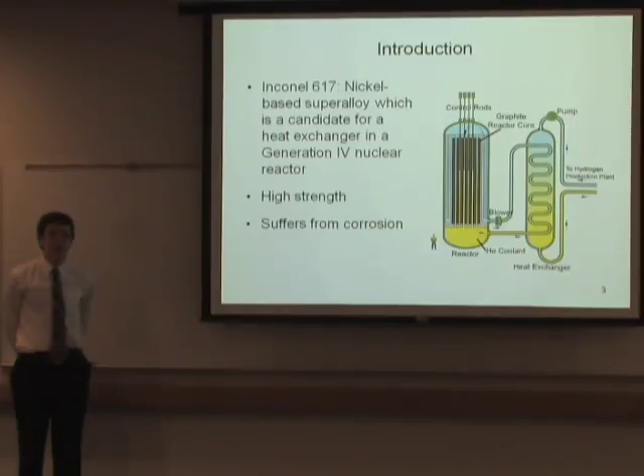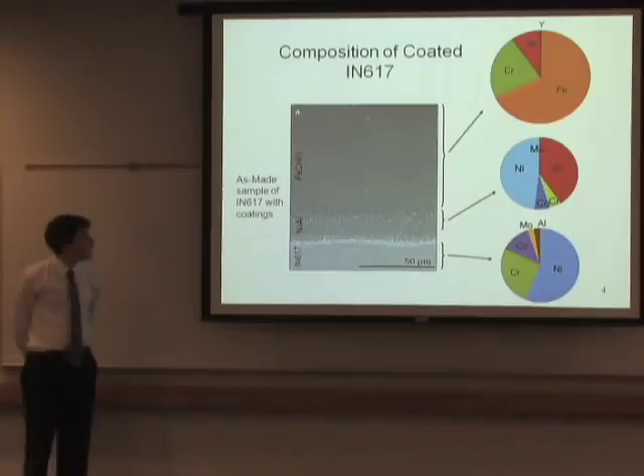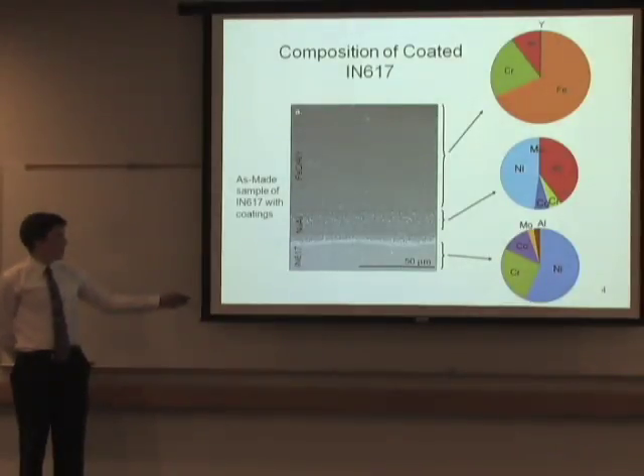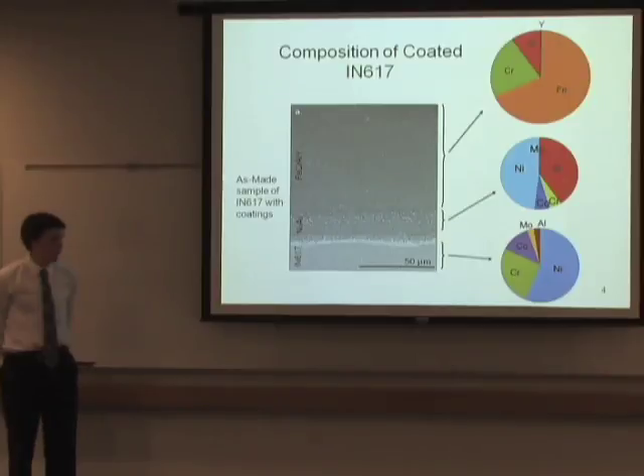So to combat this corrosion, we'll be coating our samples of Inconel with several alloys. Here is one of our samples with Inconel 617 on the bottom, composed mainly of nickel, chromium, cobalt, molybdenum, and aluminum. And on top of Inconel, we will be aluminizing our sample with something called NiAl, nickel aluminide, composed mainly of nickel and aluminum. And on top of the NiAl, we'll be bonding on a substance called FeCrAlY, composed of iron, chromium, aluminum, and yttrium. And what we're concerned with is how this microstructure changes due to processes like interdiffusion. Interdiffusion is basically when elements from one substance diffuse into that of another, changing the microstructure and its properties.